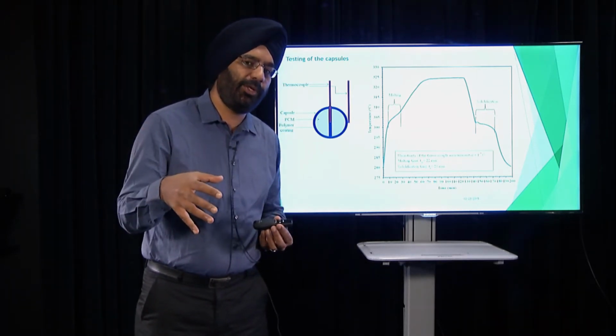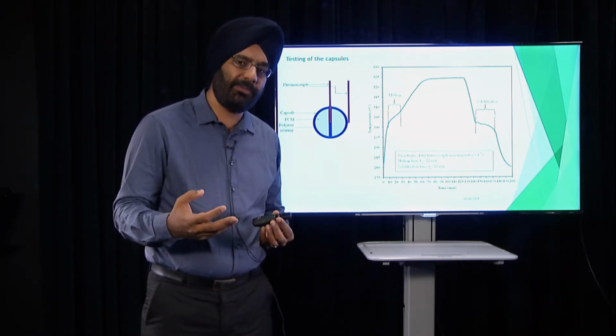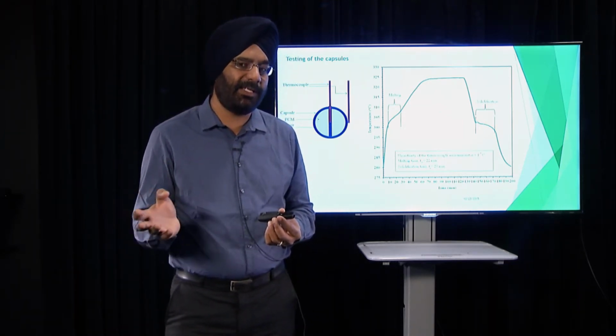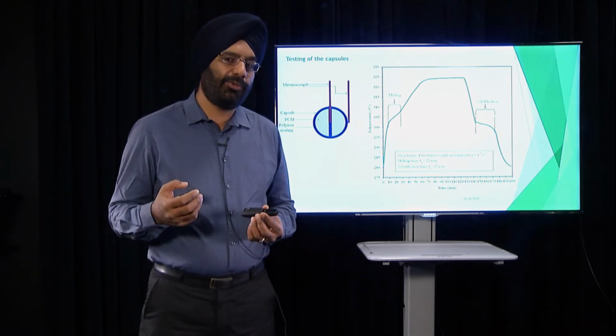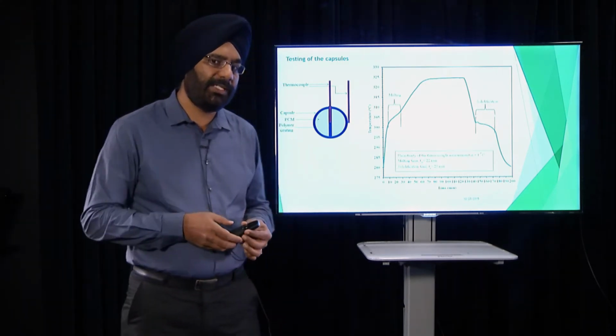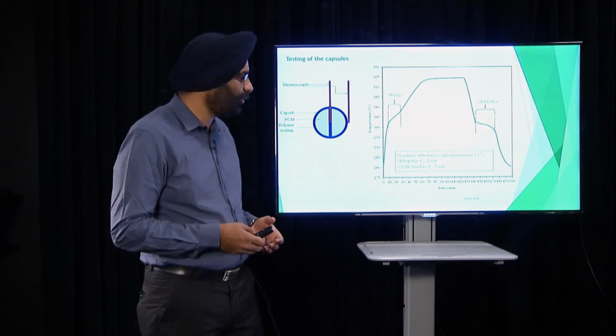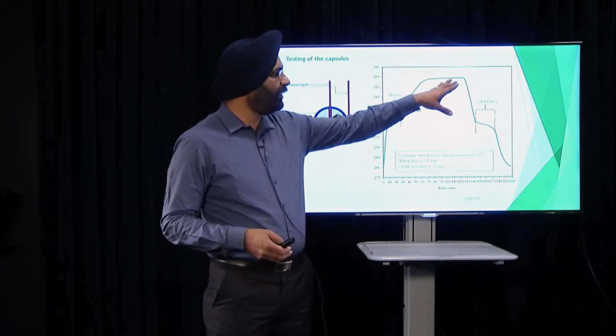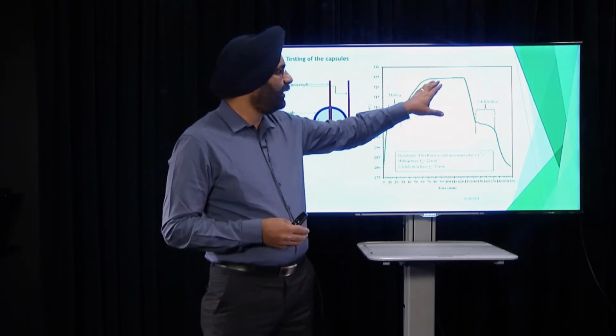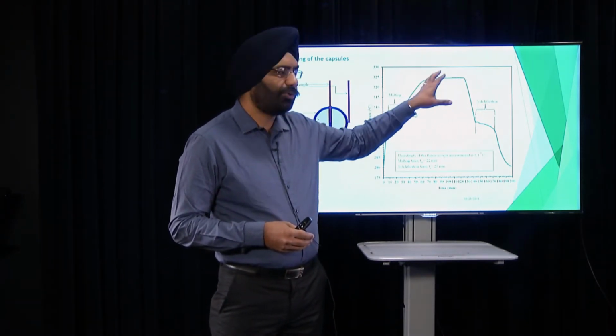It's very essential to know, because you should know how long it takes to charge a system, and then you should also know how long it takes to completely discharge the system. Remember I said that you need to generate electricity at a certain rate, because all of a sudden there is a demand, so you need to generate that electricity at a certain rate. So you need to know how long it's going to take to charge and how long it's going to discharge. So it went up to like 326 degrees C, which was the temperature set on the furnace, and the capsule reached that temperature, and that's the reason you don't see any change in the temperature in there. That was the furnace temperature.